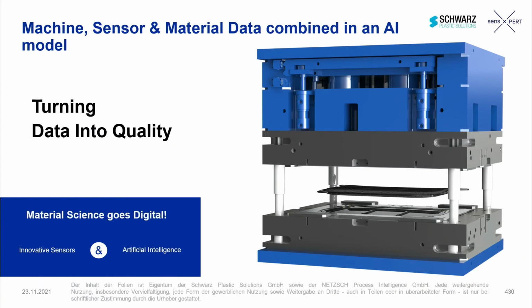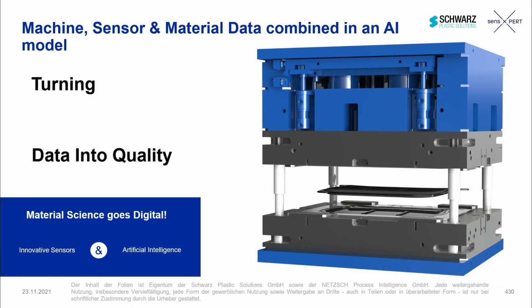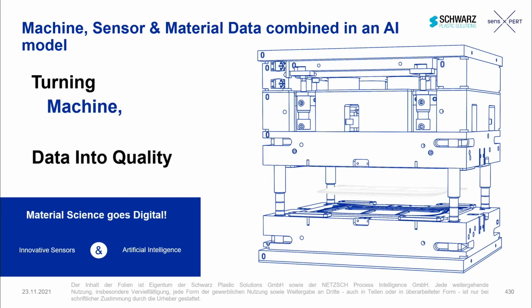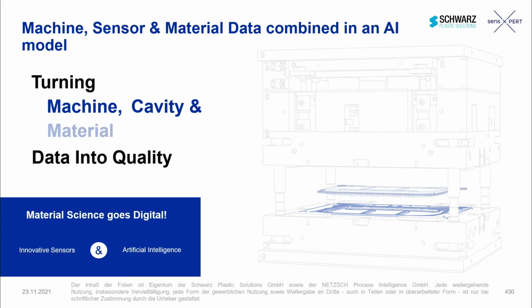In principle, we collect data from three different sources during the production environment. We use the machine data, we use the cavity data, so sensor data out of the mold, be it our dielectric signal to collect data on the material behavior, or pressure or temperature sensors. And we also use material data. Here we talk about reaction kinetics, the physics and chemistry behind the behavior of polymers. Combining all three sources of data, we can see the dependencies between process parameters and material behavior, and therefore readapt the process to different states of the material.